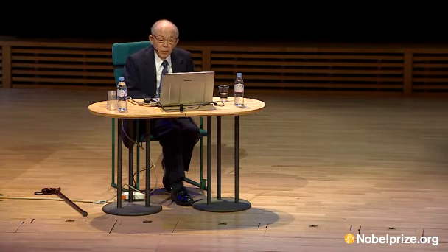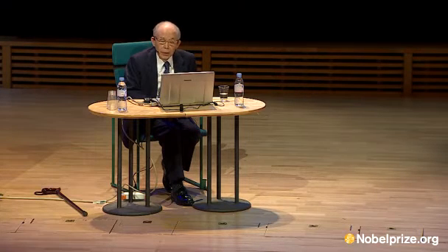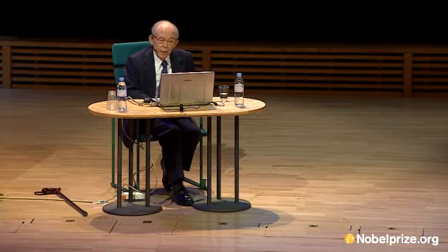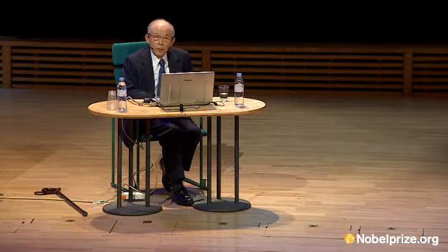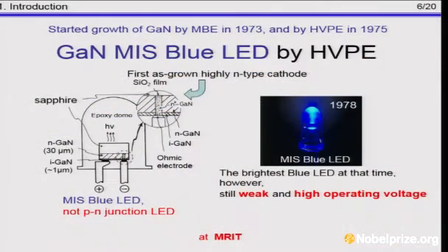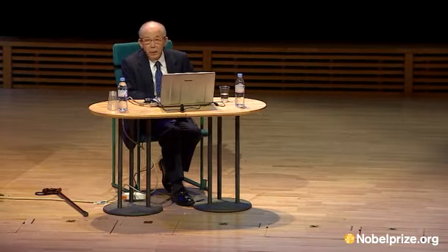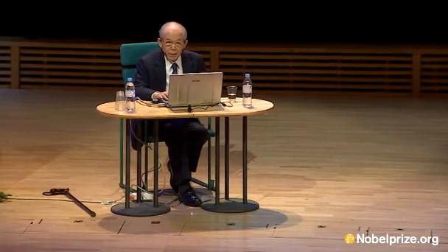I started to grow gallium nitride by molecular beam epitaxy, MBE for short, in 1973. Then, by hydride vapor phase epitaxy, HVPE for short, in 1975. And in 1978, my group at MRIT developed MIS-type blue LEDs, which were far brighter than anything one had before. Although it was no comparison to the p-n junction LED, which we invented later in 1989.